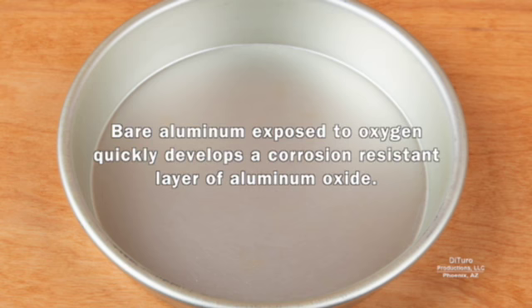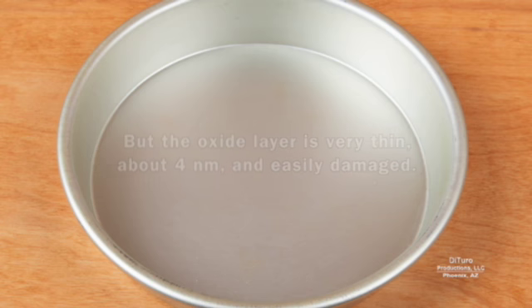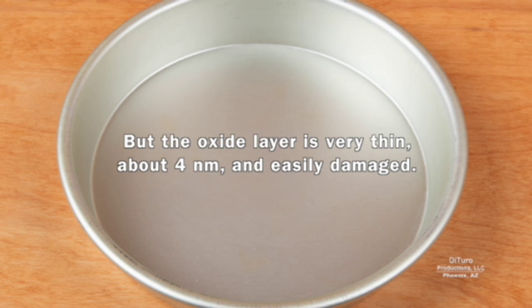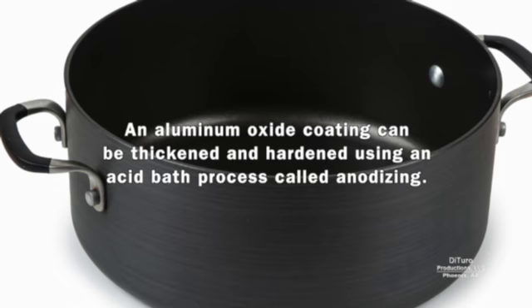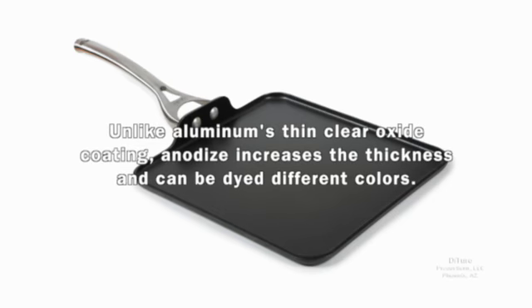Bare aluminum exposed to oxygen quickly develops a corrosion-resistant layer of aluminum oxide. But the oxide layer is very thin, about 4 nanometers, and easily damaged. An aluminum oxide coating can be thickened and hardened using an acid bath process called anodizing. Unlike aluminum's thin, clear oxide coating, Anodize increases the thickness and can be dyed different colors.